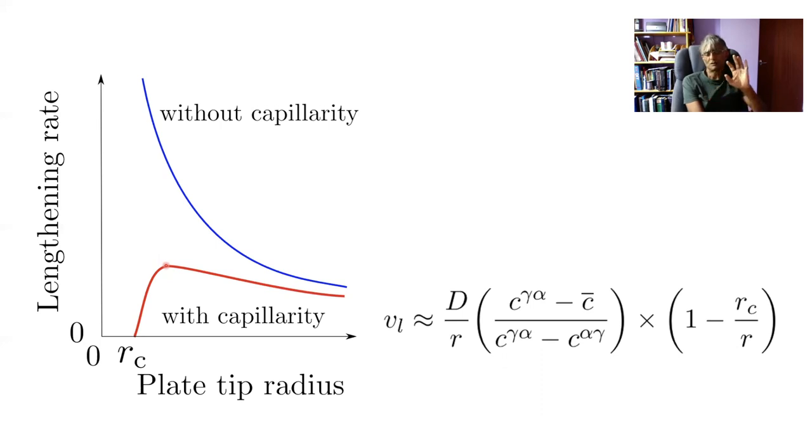So this cannot be formally justified because you could have a maximum entropy production rate, for example, and various other criteria. We can ignore interface stability criteria because this is a displacive transformation, and therefore its morphology is determined entirely by strain energy minimization. But let's assume that the plate grows with a tip radius that gives us the maximum growth rate.